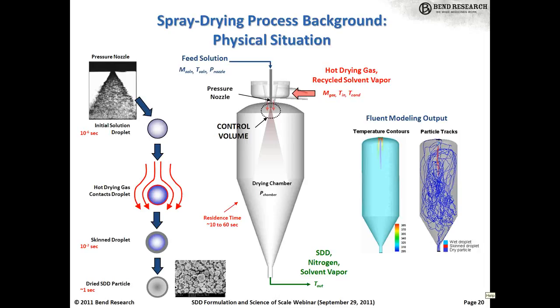The drying process happens relatively quickly. Within seconds, you end up with your dried particle. So we tend to focus on the key control volume up near the atomizer, where the droplets are formed and dry very quickly to define your particle morphology. And that key control volume up near the drying gas disperser is illustrated by a couple of computational fluid dynamics model outputs shown here on the right of this slide, illustrating that point. There's a temperature contour showing that the temperatures within the dryer are mostly at the outlet temperature of the dryer, with the exception of a colder evaporative spray plume up near the drying gas lid.